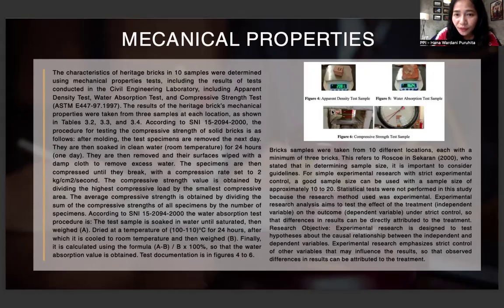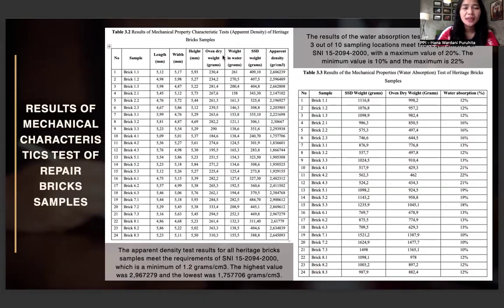And we can see in the pictures, figures 4, 5, and 6, we have tests for apparent density, water absorption, and compressive strength. We can see the results in the table. The apparent density test result for all heritage brick samples meets the requirement of SNI, which is a minimum of 1.2 grams. The highest value was 2.9 and the lowest was 1.7. So we can see at table 3.2, many samples.